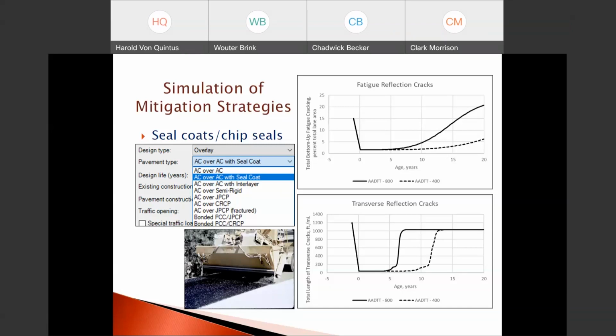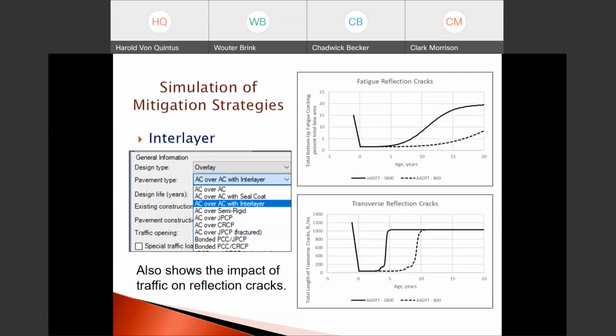The one thing I'm going to remind everyone, that I mentioned earlier, is that the predicted fatigue and predicted transverse cracks, where we have AC over an asphalt overlay with seal coats, the predicted amount would be very similar if we just had an asphalt overlay over an existing flexible pavement, with and without a seal coat. There's not a big difference in the predicted cracking between those reflection cracking mitigation strategies. The same is true for interlayers, for the reasons I gave near the beginning of the webinar.